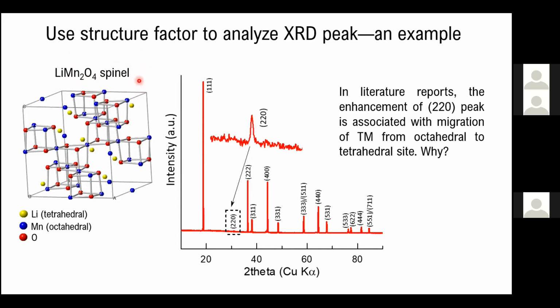So you see this is the cubic-based F lattice. Because of this F, we see HKL can only be either all odd or all even, right? So this all even, all odd, all even, all odd.